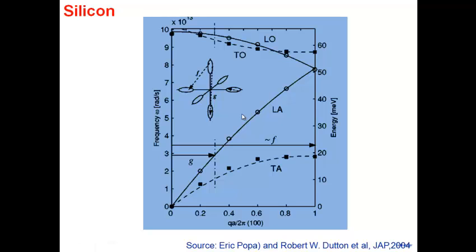Look at the typical energies of the phonons. Acoustic phonons are low energy, 20 milli electron volts or so at the highest point, and then it reduces. While optical phonons, note that the optical phonon energy is all high. The minimum that we see here is 50, otherwise it is higher; all these energies are on the higher side. So optical phonons are higher energy phonons. Acoustic phonons are available at lower energy and also at moderate energies.